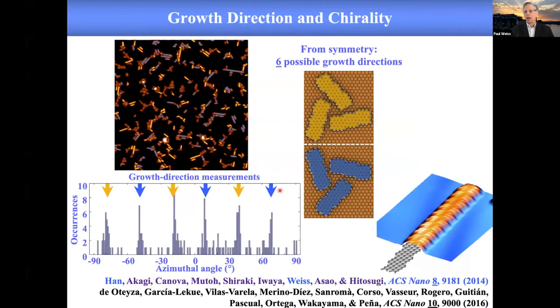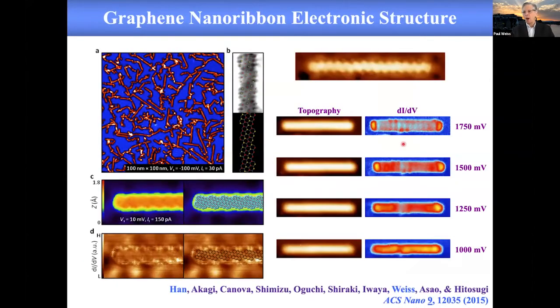And then Nacho Pascual, a former postdoc in the group, now in San Sebastián at Nanogune, took the next step and worked on a vicinal surface in which the terraces were all in one direction and sufficiently narrow that he got one chirality everywhere on the surface. And we were able to do the spectroscopies of these. We could do things like slide a halogen atom up to the edge of the graphene nanoribbon and quench the state and change basically what's a particle in a box to particles in two boxes by putting a node into those systems.